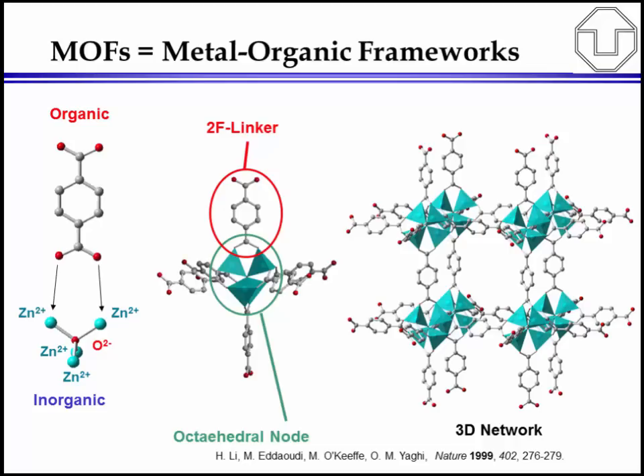So in this way, a very highly porous architecture is achieved, and this was one of the breakthroughs in metal organic framework chemistry, because here for the first time, a surface area of 3,000, 4,000 square meters per gram was achieved in MOF5, and this was more than in traditional zeolites and even activated carbons. Next slide, please.